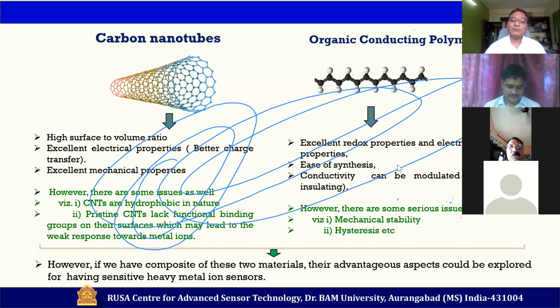Similarly, organic conductive polymer has certain advantages and disadvantages. What are the advantages? It has excellent redox properties and electric charge transfer properties. Ease of synthesis, conductivity can be modulated like anything. However, although there are some advantages, there are certain problems as well. What are those problems? Mechanical stability is going to be one of the great issues. But if you synthesize organic conducting polymer at nano level, obviously the stability can be enhanced significantly. And moreover, if you are using this for a sensor, hysteresis is going to be one of the great headaches for organic conducting polymer.